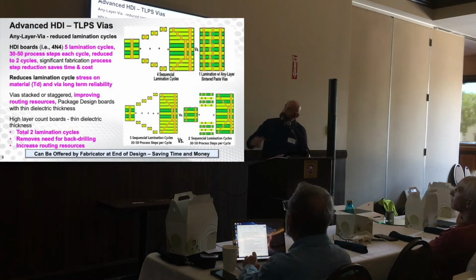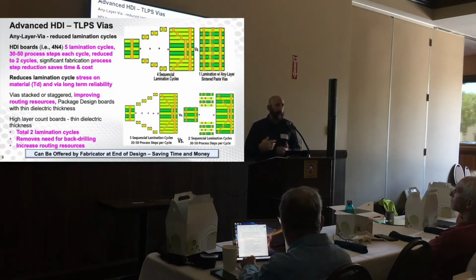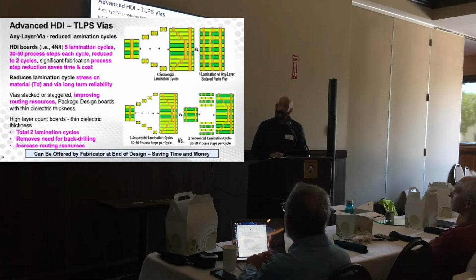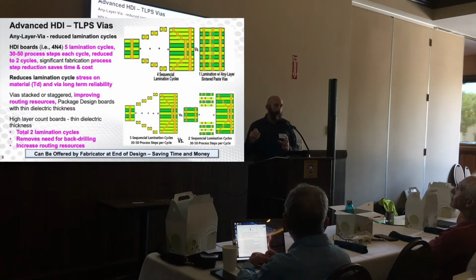So just some examples of cutting out the lamination cycles and giving you freedom to be able to place vias anywhere you want. And again, the idea is you're forming the interconnect between the layers during lamination instead of laminating first and then plating later. So it actually eliminates the plating process. There are some mobile applications for this where, instead of going through the plating shop 4, 5, 6 times, you only go through the plating shop once and then you put all your layers together with the Ormet.